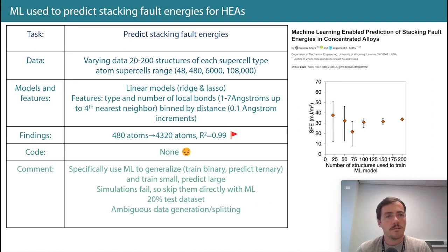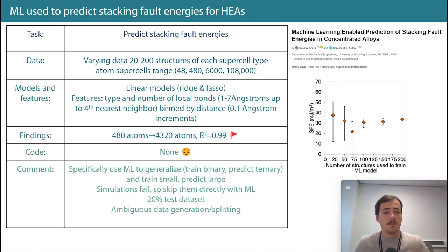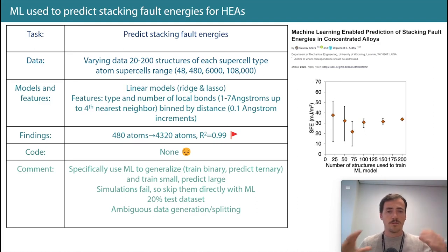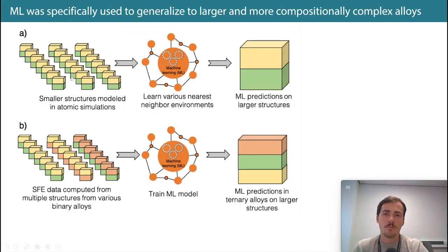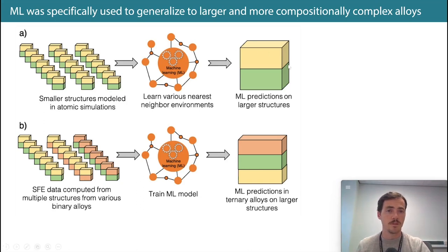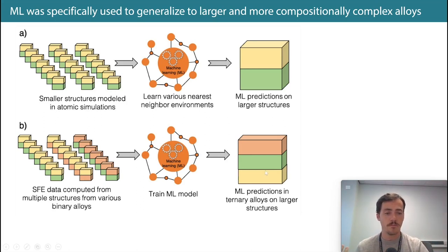The last paper is by Arora in the Metallurgical and Materials Transactions journal, a 2020 paper. They're trying to predict stacking fault energies. The data varied from 20 to 200 structures of different supercell types — ranging from 48 atoms to 480, 6,000, or over 100,000 atoms. HEAs are disordered, so you need large supercells for accurate simulation. I think what they were testing is: if you train on small, fast-to-compute models, can you use ML to extrapolate to larger supercells? Or similarly, if you train on binaries, can you extrapolate to ternaries? That seems to be what they're after.